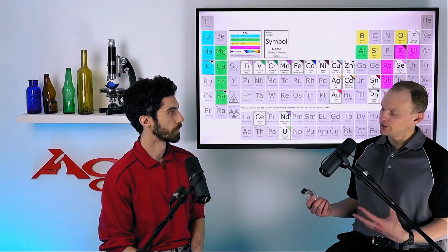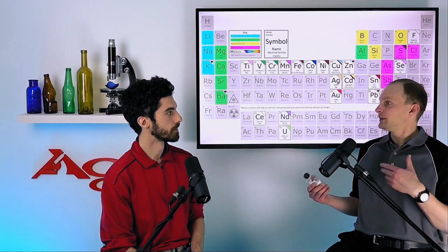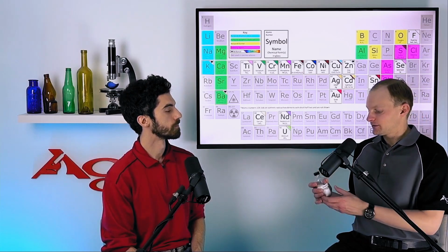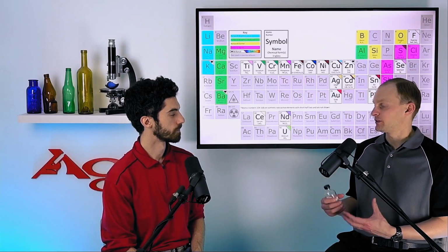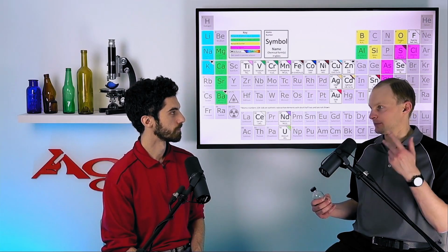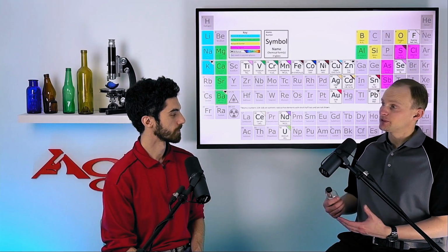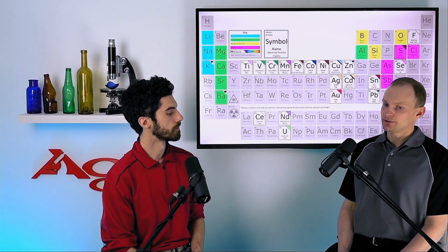A major part of that is the soda part. Soda is just the common English term for sodium, and soda ash specifically is sodium carbonate. So this sodium carbonate gets put into your batch as one of the major ingredients of that soda lime silica. So why is it this sodium carbonate form? Well, that's what's typically mined out of the earth. That's what we are going to use as a raw material.